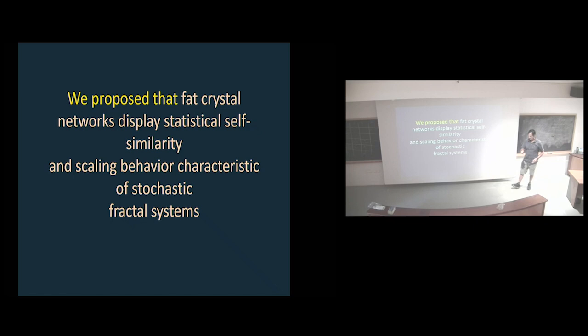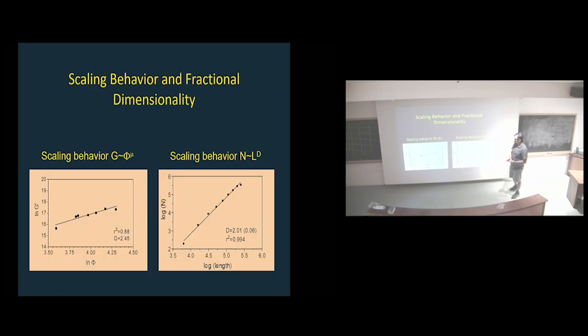I had to weather a lot of abuse, but we observed basic things like a scaling behavior of the elastic constant with the volume fraction of solids, sort of a straight line, and I call it D, but with a power law that we assume is in the weak link regime, and we end up with numbers that are more or less related to what people that simulate colloidal aggregation were getting. Even though I had so many discussions about what lives in 3-dimensional space and 2-dimensional space, you wouldn't believe it. Still, people frown at you if you put fractal dimensions of 2.5 and still yell at you when you do that, but I don't know why still.